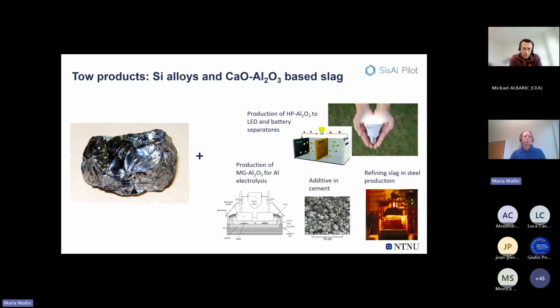So as said, what we produce in this project is this SisAl alloy, a mix of calcium, aluminum, and silicon, mainly silicon, that you will see later on that we refine in this project. We have the slag, which needs to be utilized because we see that as a product as well, which can either be used to produce high purity alumina. You can put it back to the electrolysis cells and produce aluminum again, or you can use it as an additive in cement or as a refining slag in steel production.